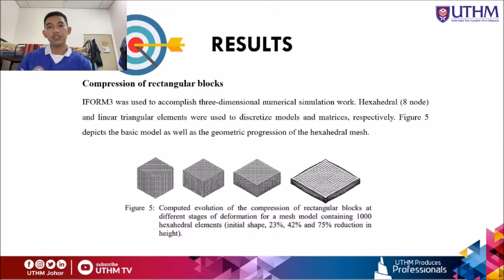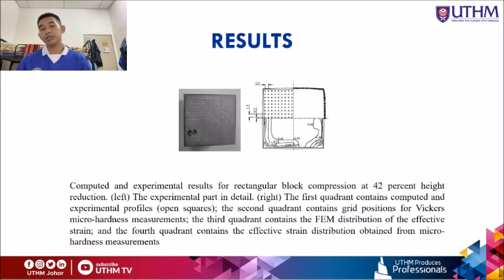Figure 5 shows the computed evolution of the compression of rectangular blocks at different stages of deformation for a mesh model containing 1000 hexahedral elements: the initial shape, and 23%, 42%, and 75% reduction in height. Computed and experimental results for rectangular block compression at 42% height reduction.